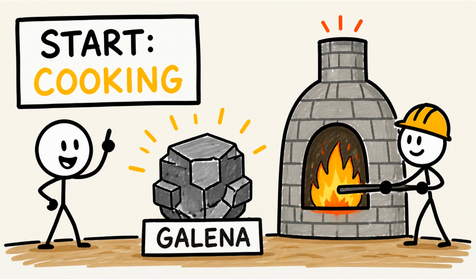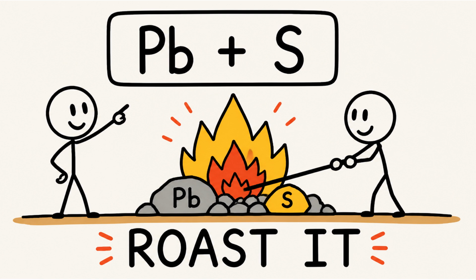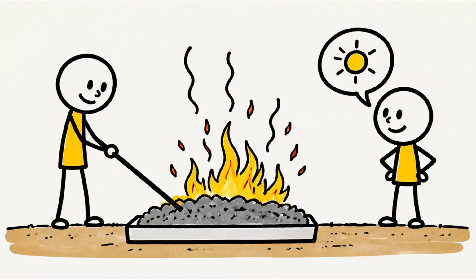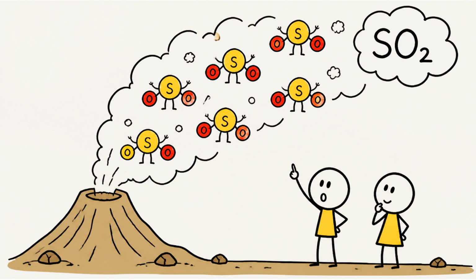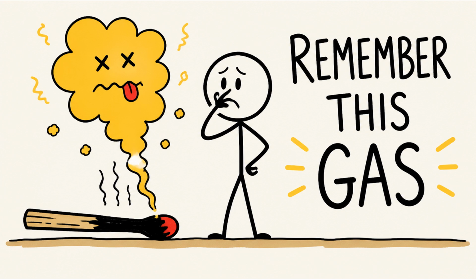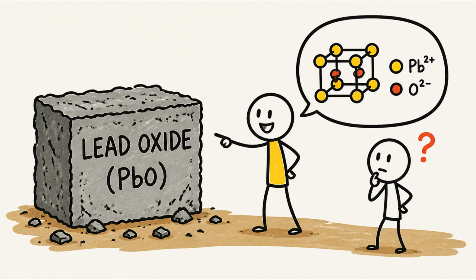Let's start with the cooking. Remember what that concentrate actually is? Galena. Lead locked onto sulfur in a compound called lead sulfide. Step 1 is to get rid of the sulfur, so they roast it. The concentrate is spread out and burned in open air, and the sulfur reacts with oxygen and floats away as a gas, sulfur dioxide, that sharp, throat-catching smell of a struck match. Hold that thought about the gas, by the way. It matters later. What's left behind once the sulfur is burned off is a crumbly gray solid, lead oxide.